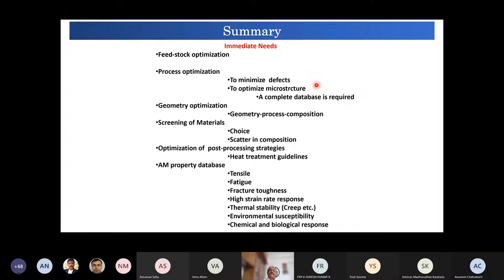Like in IISc, the claim to fame of our department is to generate processing maps, which were developed by senior professor, Professor YVRK Prasad. He has generated a compendium of processing maps of 200 engineering materials, which was published by the American Society of Metals database. So it is published in two volumes. A similar book has to come out for all additively manufactured materials, covering all the process parameters, so that anyone can just take up the book and find that Ti64 under this condition gives the best microstructure, and in this condition it gives the best concentration of defects or elimination of defects. The whole thing is very highly desirable. So this is one thing which people have to pay attention to. Our group is working, but many more groups should work in this area.